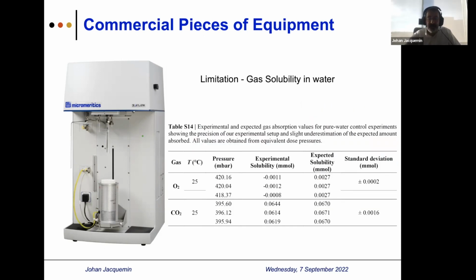And then there is a limitation of the technique. How is it possible to determine the oxygen solubility, because the group was unable to determine the pure oxygen solubility in water with the technique. And of course, they then argue that by adding the porous material, they boost it up, and the oxygen solubility in water was below the detection limit, but no problem was seen when measuring CO2, for example.